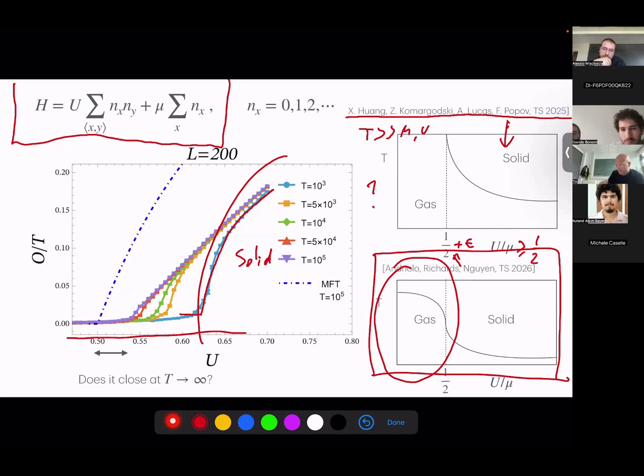I will tell you what we can prove. If we take temperature strictly infinity, then we have configurations which are either order A or order B. We never have domain walls between them. They're all killed at infinite temperature. Where the proof fails is at finite temperature, we don't know how to argue that these domain walls don't immediately appear. So infinite temperature is just not physical, and I don't know what our proof there means. But it's very difficult to imagine that when you go from infinite temperature to finite temperature, all of a sudden you have disorder, right? Because you usually have domain walls and they have some finite tension. This tension goes to infinity as you send temperature to infinity. So that's the step which we cannot prove.